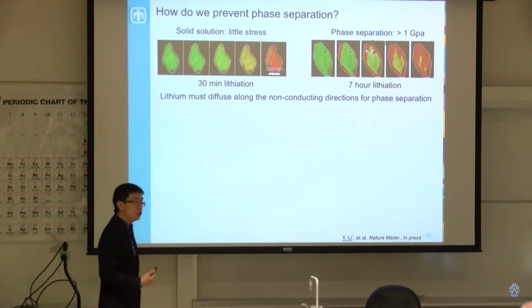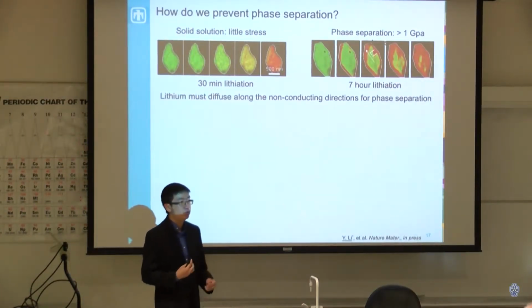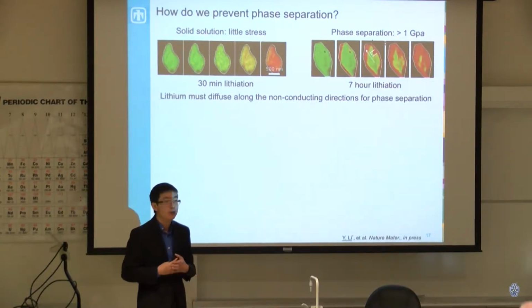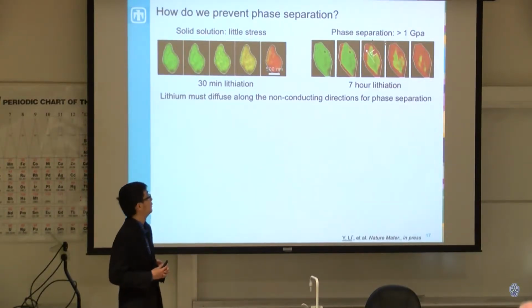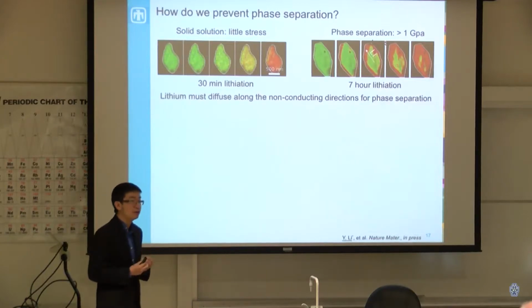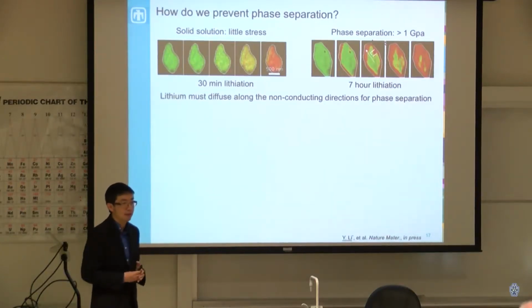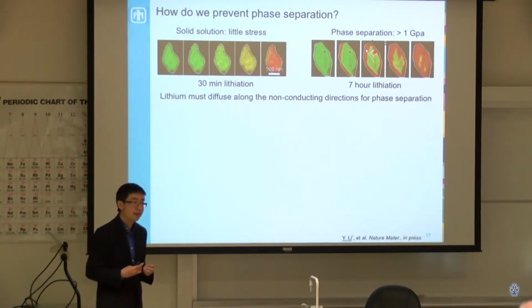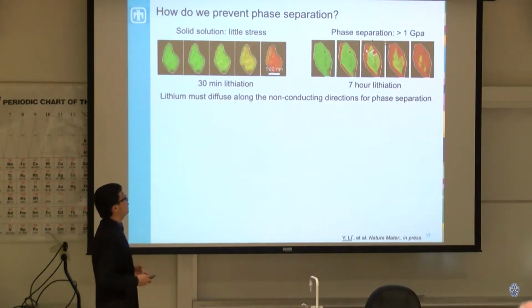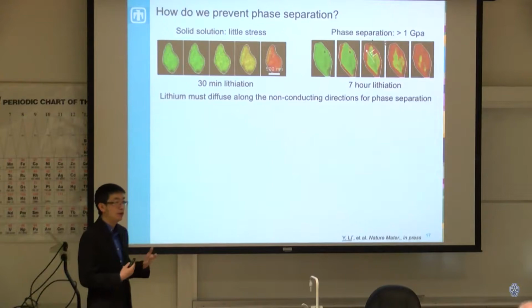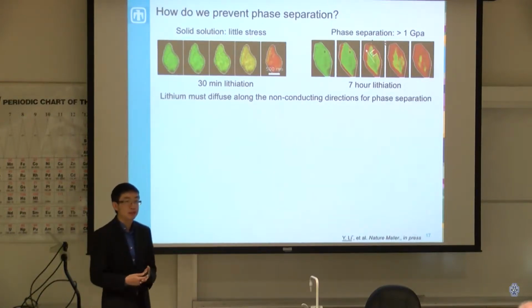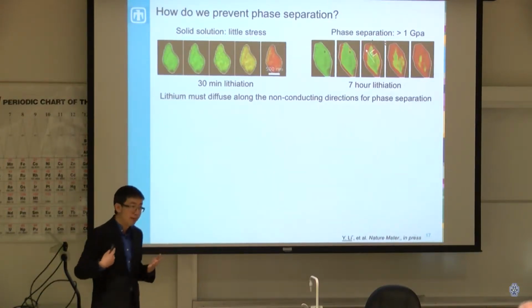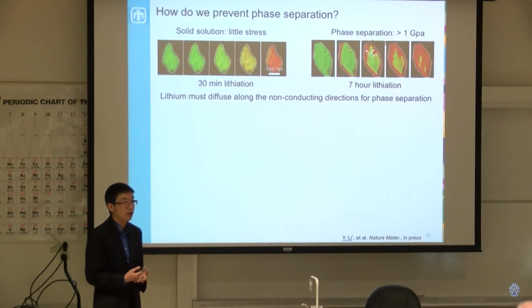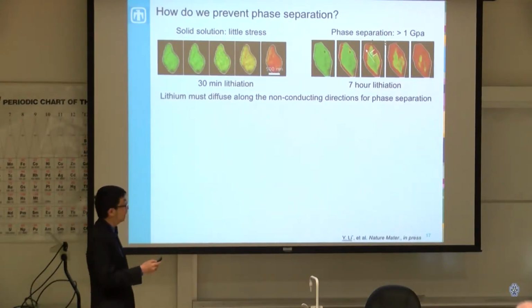So we want to engineer batteries that have minimal mechanical stress, to have more solid solution character. One way we can do that is just to charge our battery faster, but we don't really want to do that because it will degrade other parts of the battery. So instead, we're thinking about ways we can try to minimize this phase separation. Can we suppress phase separation in this material and prevent it from happening altogether?